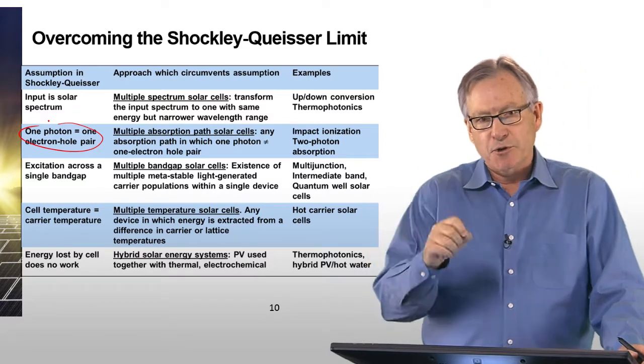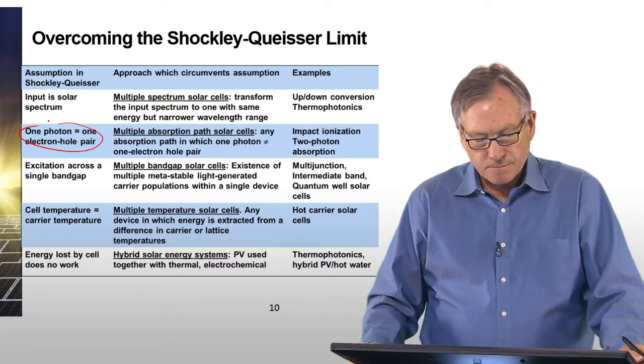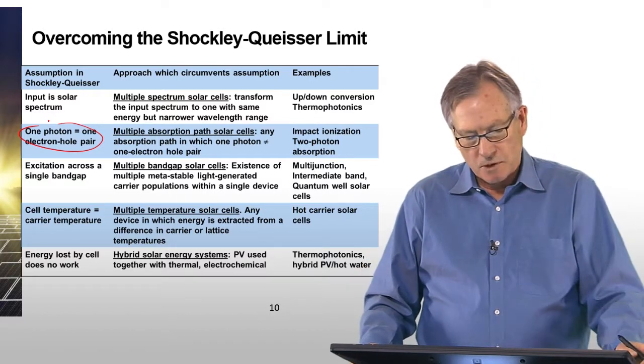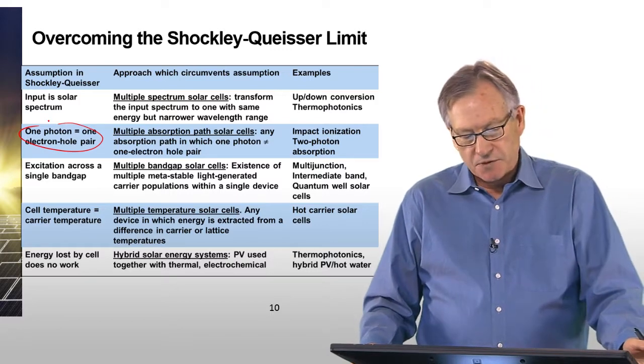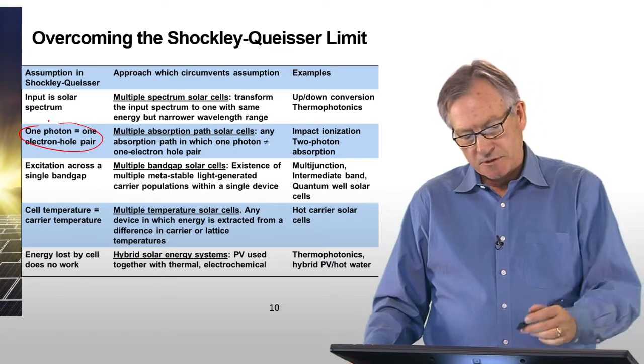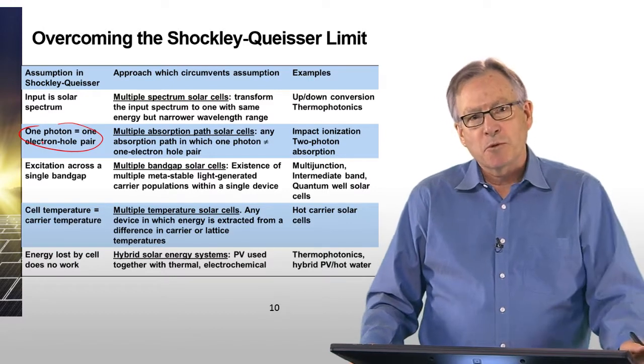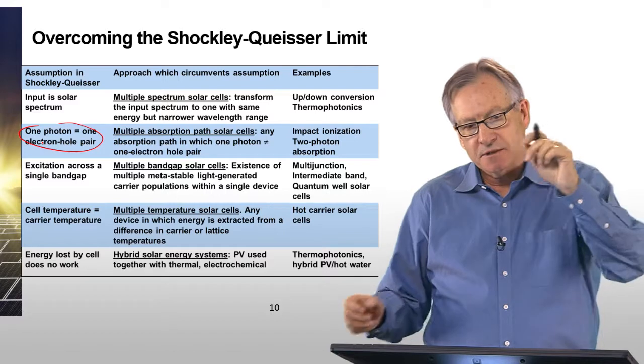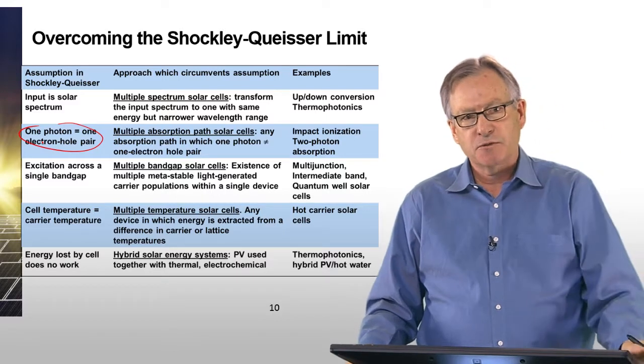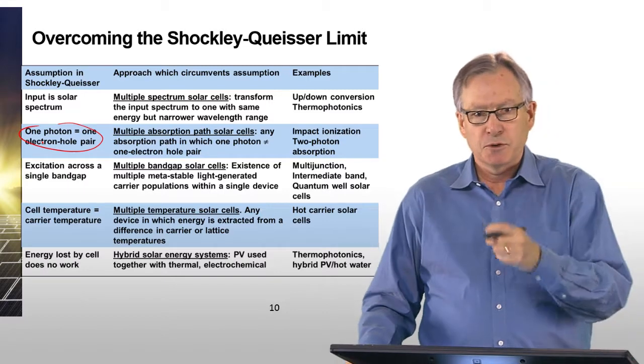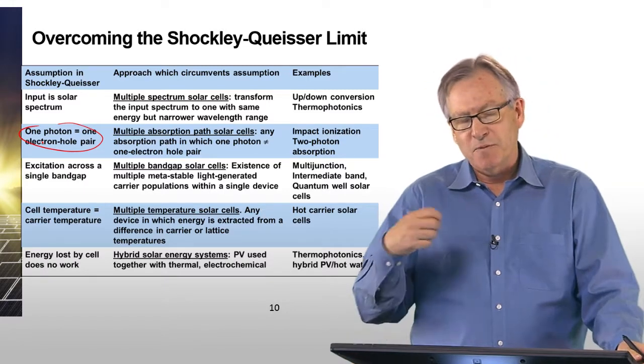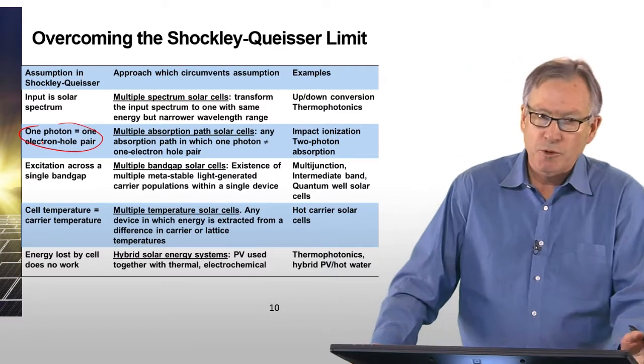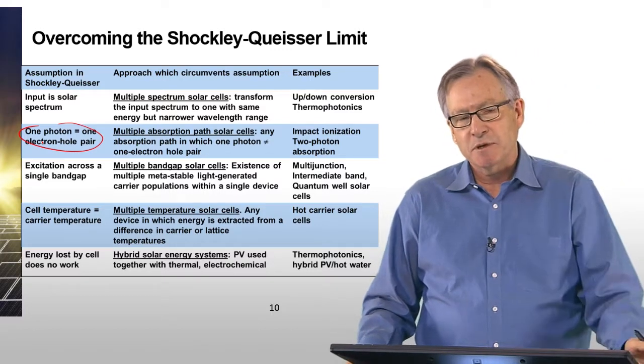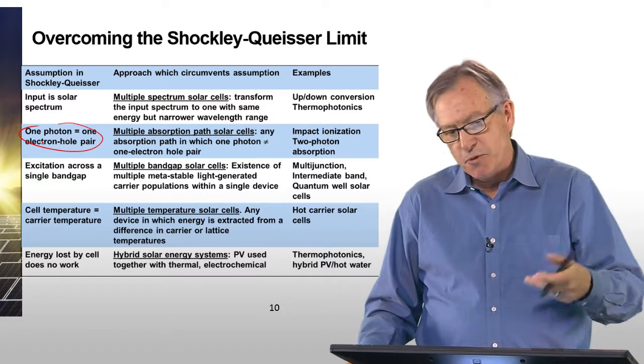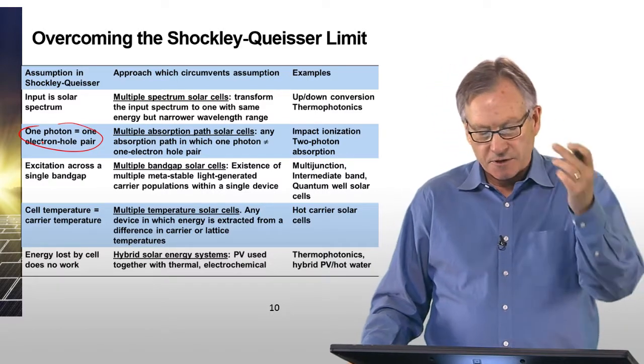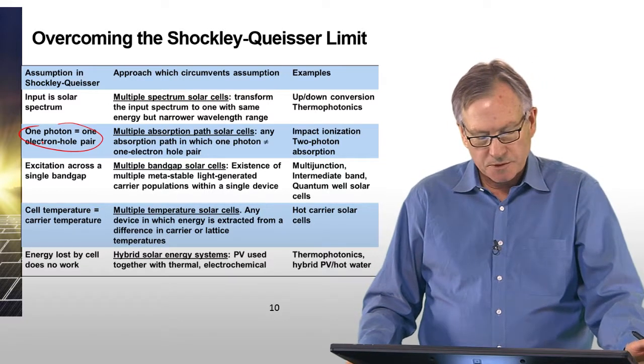Another issue is the assumption that you have one photon and that creates one electron hole pair, and that only occurs when the energy of the photon is greater than the band gap. But there are multiple paths to create electron hole pairs. You can have a high energy photon that creates an electron hole pair, but before that electron hole pair can relax, the high energy electron can actually create a second electron hole pair. So in that way, you can get two electron hole pairs for a single photon and circumvent the Shockley-Queisser limit. You can also have two photon absorption, which would allow subband gap photons to be absorbed, two of them at a time, to kick up an electron from the valence to the conduction band. That would also circumvent the Shockley-Queisser assumption.